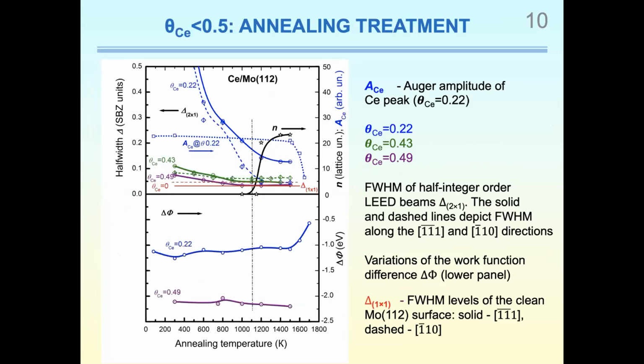Structures formed during the room temperature deposition are likely metastable due to the low adsorbate mobility. Therefore, to activate ordering in the overlayer structure, we anneal the sample at gradually increasing temperatures in the range from 300 to 1400 Kelvin. At the annealing procedure, the sample had been kept for 10 seconds at the annealing temperature and then slowly cooled down back to room temperature. Exceeding 1400 caused partial desorption of cerium, evident from an abrupt decrease of the cerium amplitude and work function difference values. This figure presents examples of variation in work function difference, amplitude, and half-widths caused by annealing at constant coverages, which are less than 0.5.